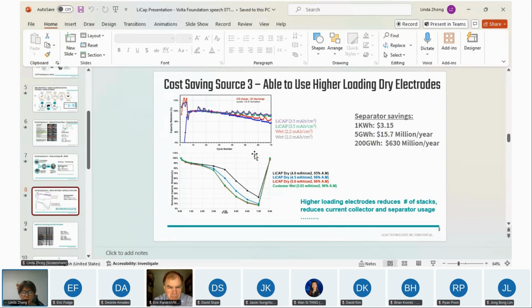So from this chart, you can see LiCap's 3.5 milliamp hour loading versus the wet electrode's 2.2 milliamp hour loading. So now we're talking about single layer active loading. You can see at the 3C discharge, comparing the wet electrode and the dry electrode, the thick dry electrode is actually more stable, right? Which means we can use 3.5 milliamp hour to replace 2.2 directly.